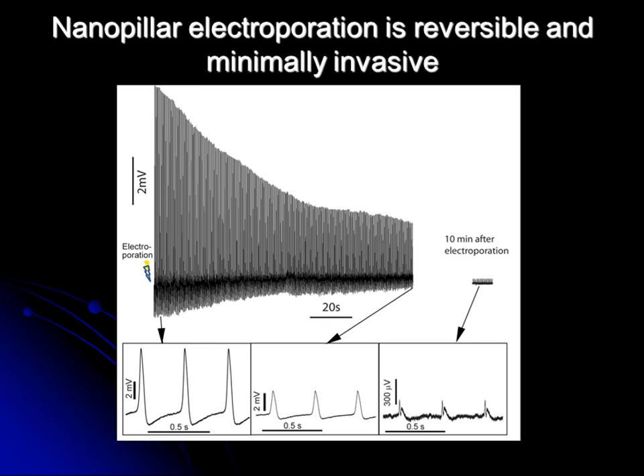However, we know that electroporation is not permanent. The pore on the membrane is not permanent. And this is exactly what we see. Cells do not like to have a pore on their cell membrane. They actively repair the pore. As a result, the data we recorded are not of constant amplitude. Instead, the amplitude decays over time in a few minutes. In the beginning, we record a very large signal. After a few minutes, the signal decays. And after 10 minutes, the cell repairs the membrane and the signal returns to the extracellular potential shape. However, it's good and bad. It's bad that we do not constantly record the same amplitude. It's good that the cell recovers and we do not kill the cell like a patch clamp.